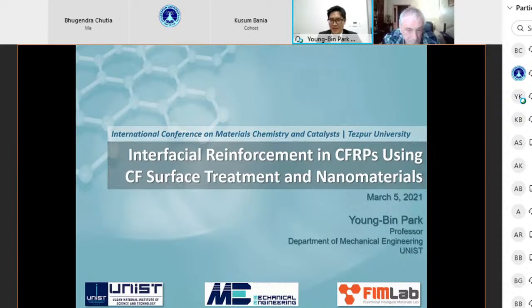So in this case, we combined carbon nanotubes and graphene into a hybrid, a freestanding hybrid sheet, which can be self-sensing, meaning if you attach these freestanding sheets on a structure, and when the structure undergoes deformation or some type of mechanical loading, any type of events or failures, then this sensing film can detect all those mechanical events.